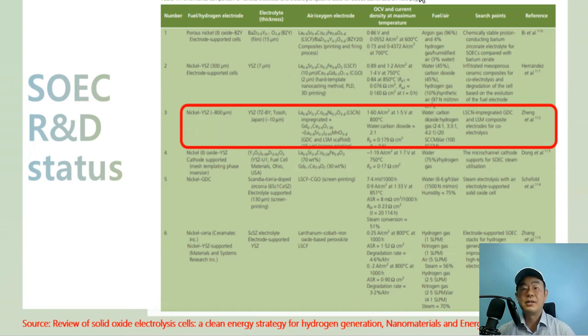This is a table that summarizes the operating characteristics of electrolyte, air electrode, and hydrogen electrode. A nickel YSZ hydrogen electrode of 800 micron, YSZ electrolyte of 10 micron, and LSCN, lanthanum strontium cobalt nickel oxide, impregnated GDC plus LSM structure in the air electrode shows a performance of 1.6 ampere per square centimeter at 1.5 volt at 800 degrees Celsius, which shows the maximum performance.